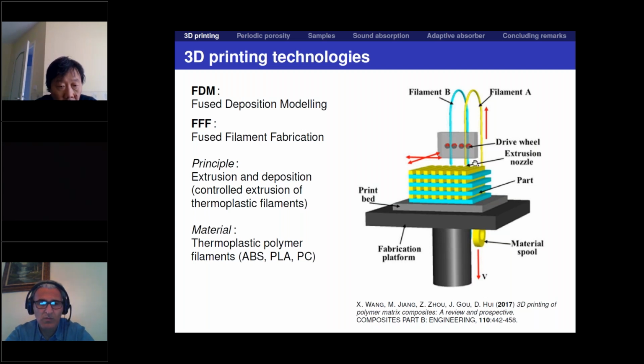And then when the nozzle is moved away, it solidifies. So we can 3D print a layer on the printing bed or on the previously 3D printed layer of the material. Actually, this picture illustrates a, let's say, dual nozzle device. So we can 3D print using two different filaments, which is important because we need to print sometimes technological supports. And we can use this second filament to print the supports because they are some kind of polymers which can be dissolved in a chemical solution.